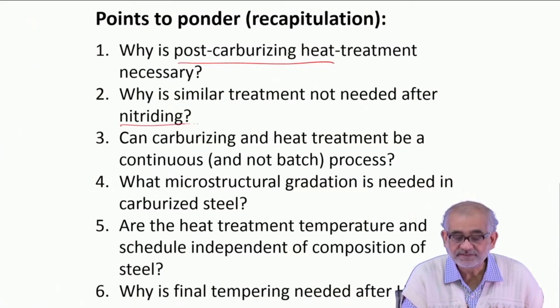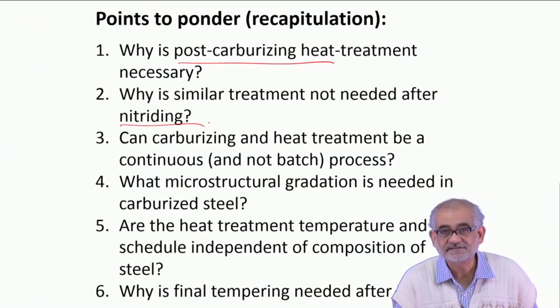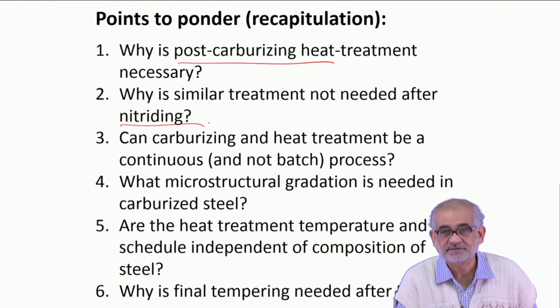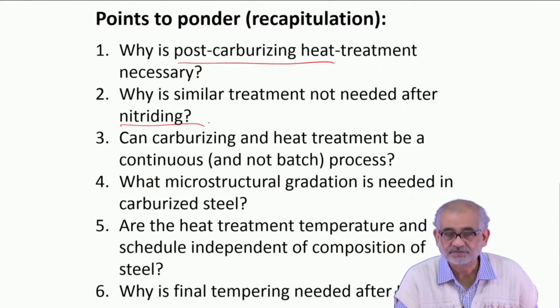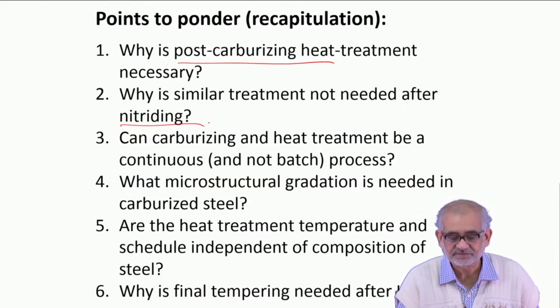We do not need a similar treatment for nitriding because the hardening is coming not from martensite but from nitrides, which are already formed during the nitriding process itself. So the material is ready for use just after the nitriding treatment.